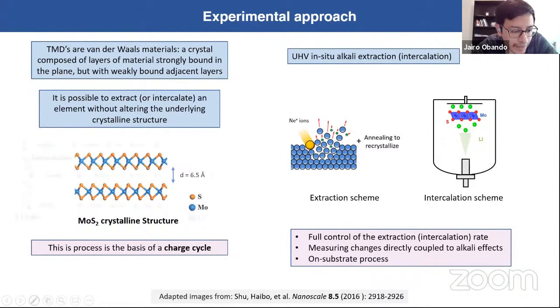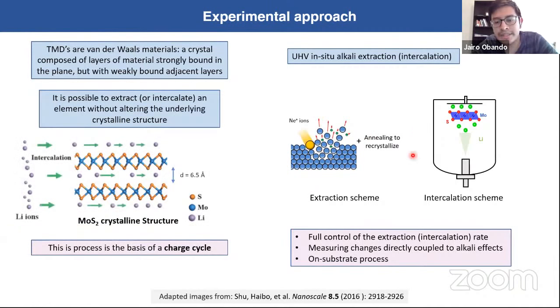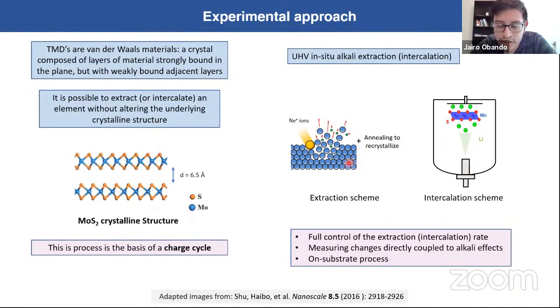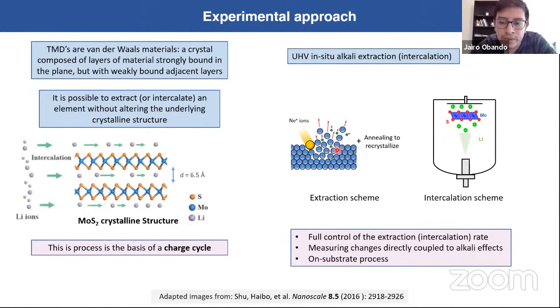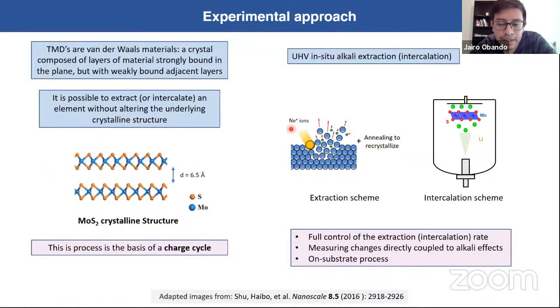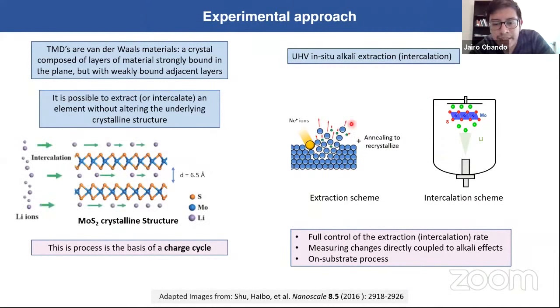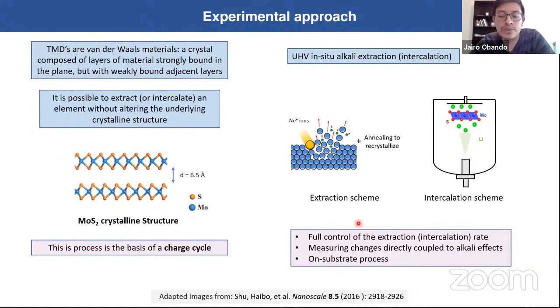In here, let me get the laser. In here, you can see two cartoons of how we experimentally do the extraction or the intercalation process. For extraction, depending on the amount of material we want to remove, we need to choose an anneal at a defined temperature, or accompany this annealing with sputtering of neon or argon atoms, depending on the cross-section that we need. And for intercalation, what we do is an evaporation with a commercial source that allows us to evaporate from lithium to cesium alkaline material. What is important is that with these two techniques, we have full control of the amount of extraction or intercalation that we want to perform.